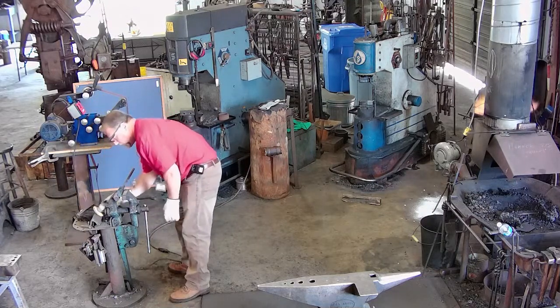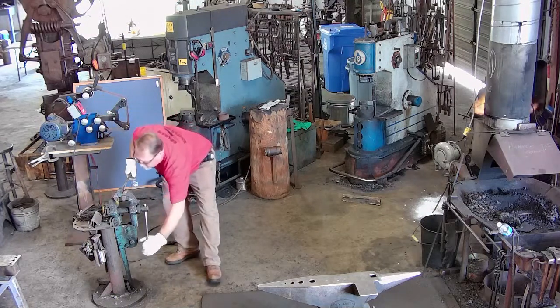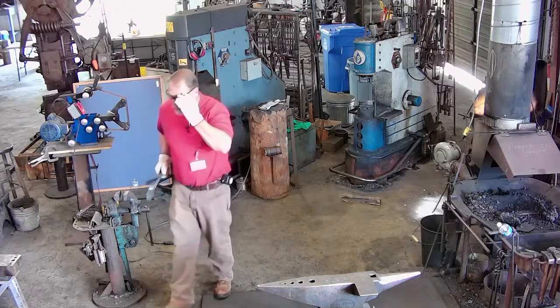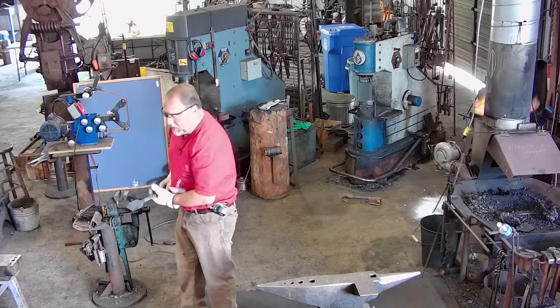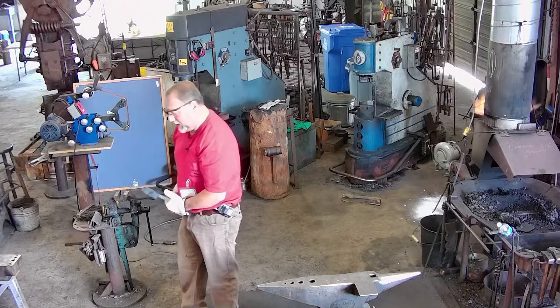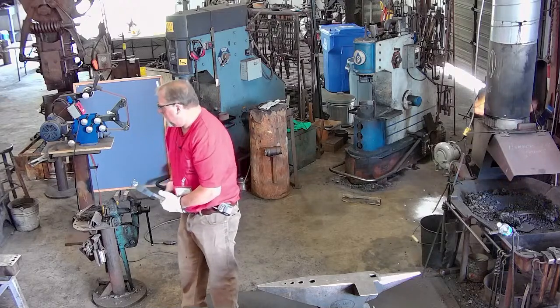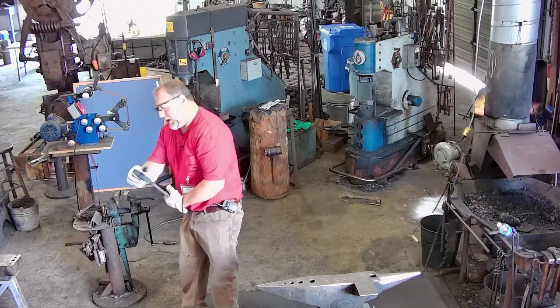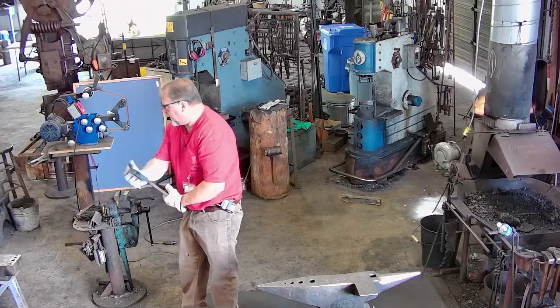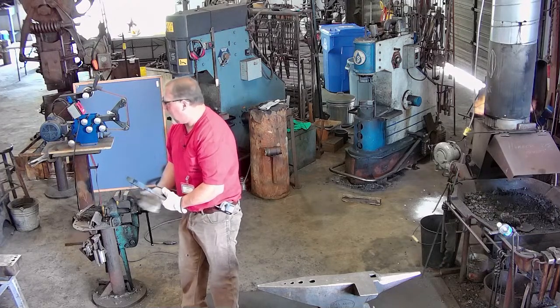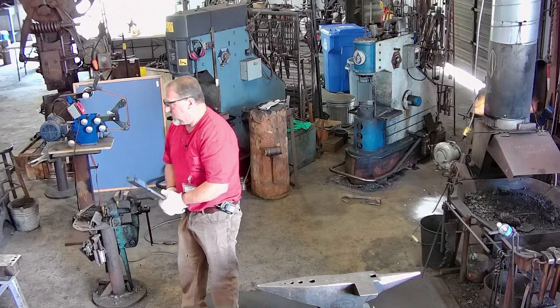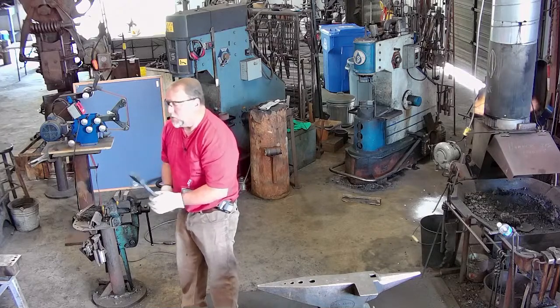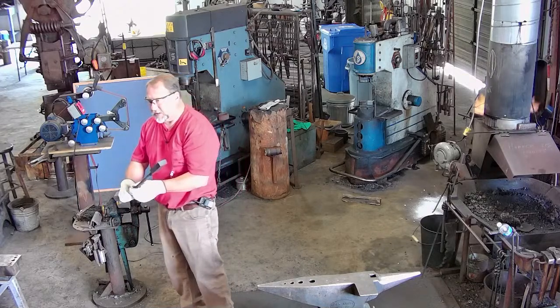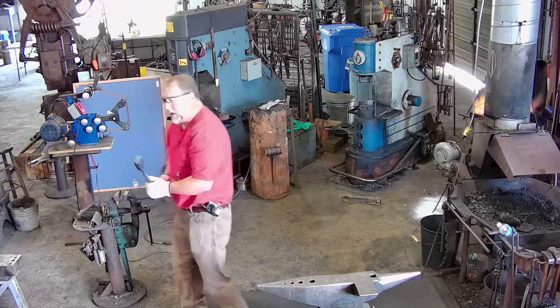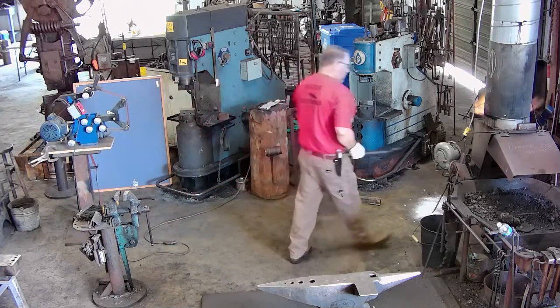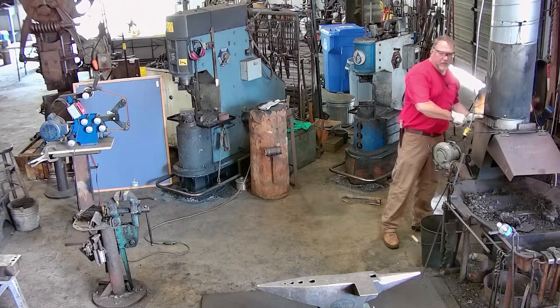All right, real quick, when you do your billet stack up, you're not going to get everything perfect. So after you set your welds initially, when you're grinding the MIG welds off, it gives you a chance to grind off the excess edges as well and line them up so you don't get cold shuts in the face of your billet. So ideally you want it to be all thin, such as this. I don't know if you see that right there.